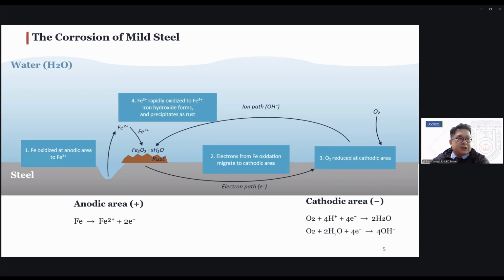Here, we can start with the anodic side. What normally happens is that the metal can lose electrons and then it's oxidized. And these electrons that are lost actually travel inside the mild steel to a cathodic area. At the cathodic area, the electrons will react with the oxygen to produce water, and then the water will give some hydroxide ions, and the hydroxide ions will then travel in the electrolyte. In this case, it's water, but there can be other types of electrolytes as well.